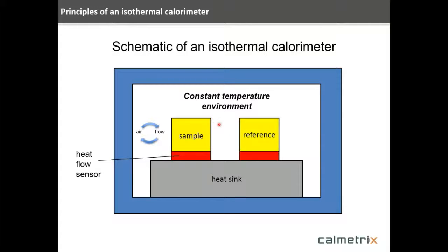This is a differential technique, so we're looking at the data in a differential form in order to improve baseline noise. The sample, both the sample and the reference, sit on top of what we call heat flow sensors. These are actually thermoelectric devices, and they in turn connect to a heat sink, in this case a large aluminum mass of metal. So this constitutes the calorimeter, and that entire calorimeter sits within this blue temperature controlled chamber. So we can control the temperature within that environment and around the sample at a very precise temperature, anywhere from 5 to 60 degrees C. So we can control that temperature very precisely.